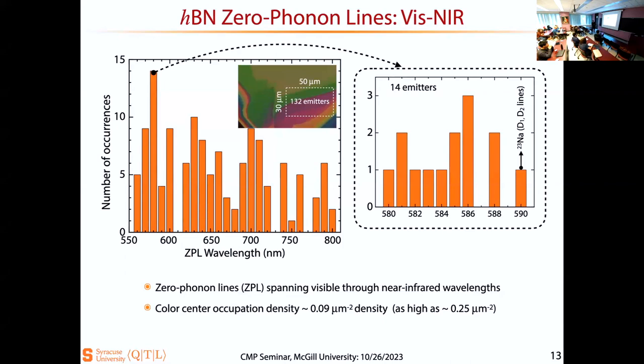One of my particular interests, when I was working in the Air Force lab, was this 589 alignment. 589 also matches very well with one of the D1, D2 lines of sodium. So this opens up the opportunity for interfacing a solid state emitter with an atomic emitter. Saying is very easy, doing is very, very tough. But they got really excited about interfacing these color centers with sodium atomic vapor. In fact, a quarter of my PhD was in atomic vapor when I was working with Sully. I was working with sodium, rubidium, cesium. These were the atomic vapors I worked with in the actual experiments.